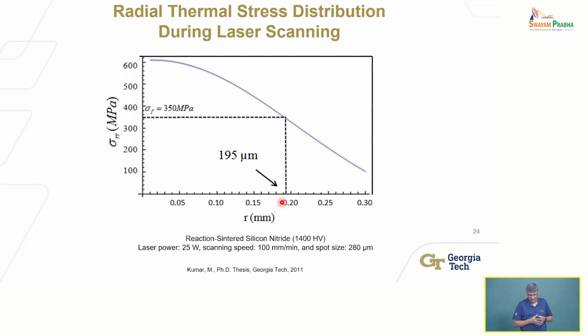So that tells me that by changing my laser power, scanning speed, and spot size, I can play with those to determine what size region I want to generate these thermal stresses that exceed the fracture strength of the material, using such a model. That's a much smarter way for us to do this, right? Rather than just trial and error, which you would have to do experimentally. It's expensive to do. You don't want to do that.